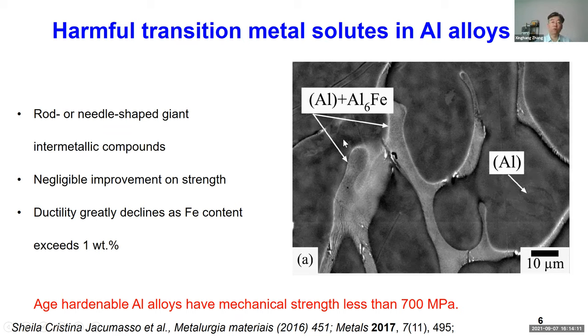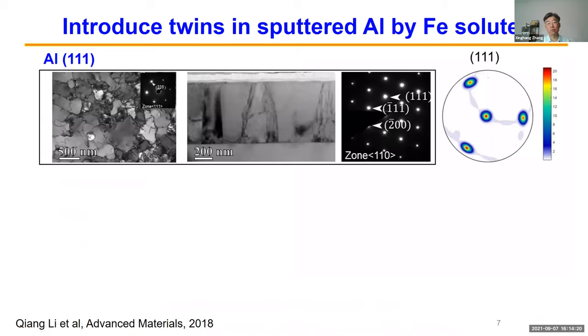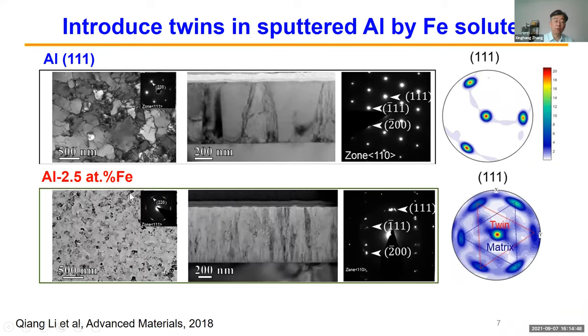So then for us, the question is, if we introduce iron through a technique other than conventional casting, for example sputtering, what does it do to aluminum? Can we get twins in there? This is the experiment my student Qiang Li did. If you simply sputter aluminum, you get single-crystal-like aluminum with some grain boundaries, domain boundaries. And if you look at the X-ray pole figure, it's a very classical single-crystal-like pattern, so threefold symmetry.